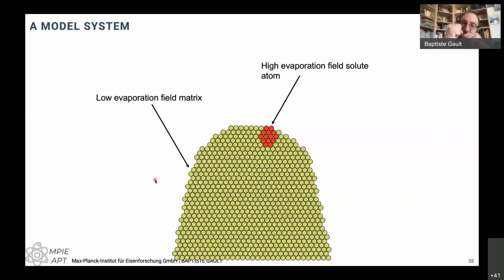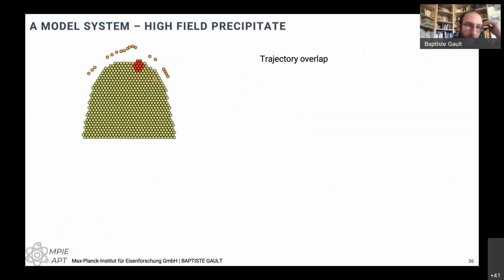So as I said, for the matrix, we have sometimes some small aberrations taking place. And it can become a bit more tricky at times because if I consider a particle inside of the matrix, the bonding inside the particle will necessarily be different. It means that I will require either a slightly higher electric field or a slightly lower electric field to remove the atoms. Which means that these atoms from the particle will not really leave in the right order, right? Because if they need a higher field, for example, the fields that I need to remove the matrix atoms and the ones from the precipitate won't be the same.